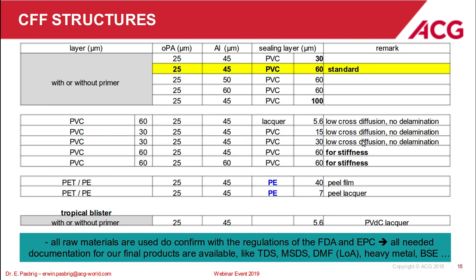The advantage of this material is a lower cross-migration of humidity and oxygen. The disadvantage of this material, if you can say so, is that it's more flappy compared to the standard material, so care has to be taken at the blister machine if this material is running. Then mainly in Asia 50 micrometer aluminum is used. Then you have the same material with 60 aluminum, 60 PVC. This is if the cavity needs a special stiffness after forming, or the cavity is relatively big. And the stiffest material from the three-layer laminates is with 100 micrometer PVC as a sealing layer, mainly used for dry powder inhalation.